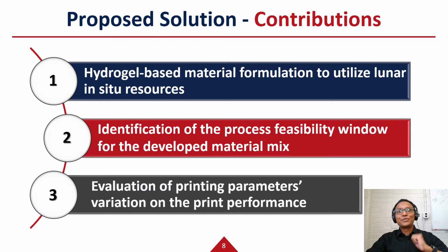This work has three major contributions. First, we developed a hydrogel-based material formulation using pluronic, water, and lunar regolith simulants that enable higher material utilization and reduces material pre-processing steps. For our developed material mix, we identified the process feasibility window in terms of printing speed and extrusion rate. And finally, we evaluated the impact of printing parameters on the print performance.